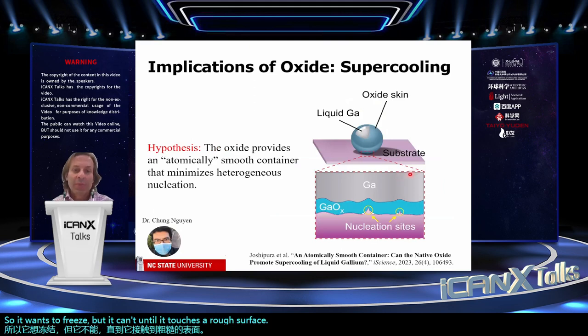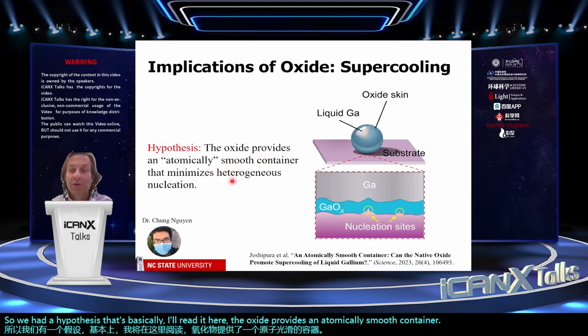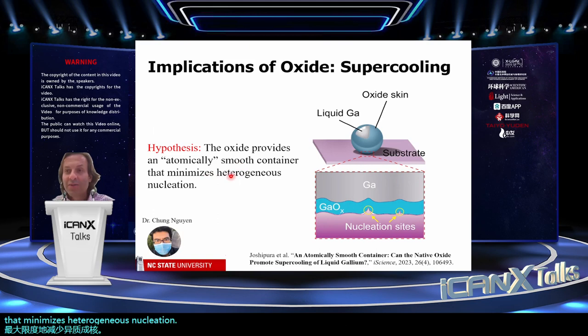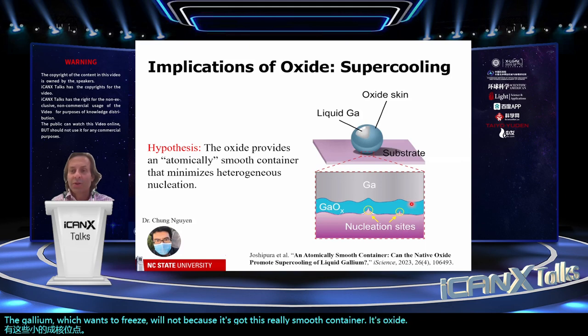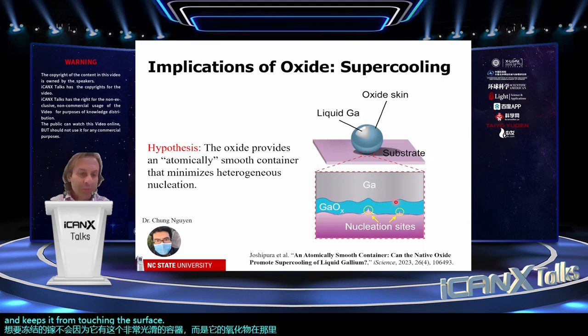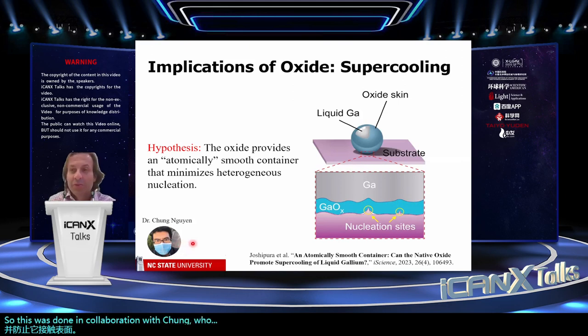So we had a hypothesis that's basically, I'll read it here. The oxide provides an atomically smooth container that minimizes heterogeneous nucleation. That's kind of a mouthful, but you can see here the basic idea that if you have a surface, let's say you have a droplet of liquid metal and it's on a surface, and there's these little nucleation sites, the gallium, which wants to freeze, will not, because it's got this really smooth container. It's oxide there that holds it and keeps it from touching the surface. So this was done in collaboration with Chung, who worked with a student in my group.